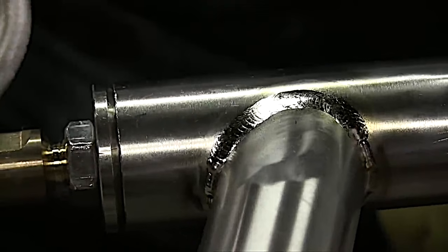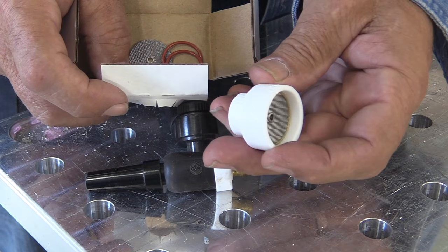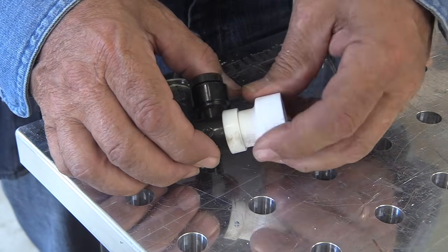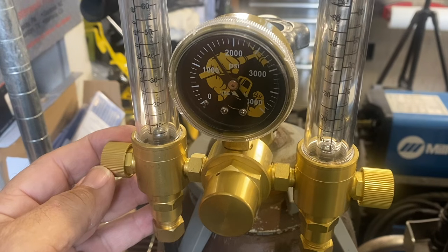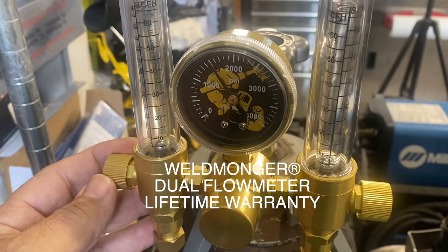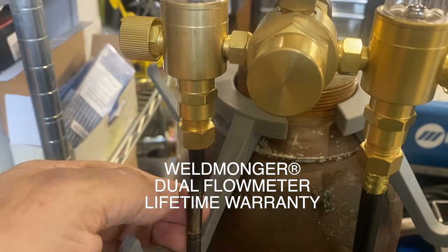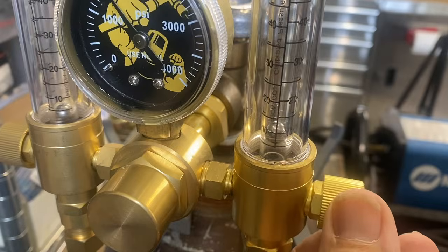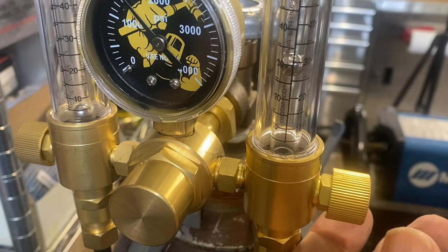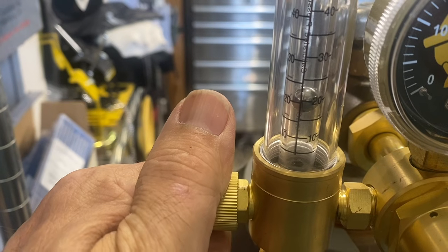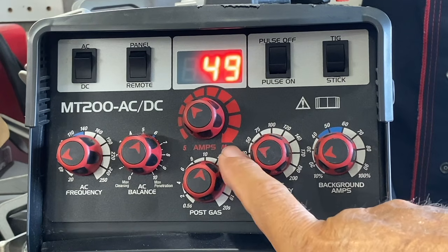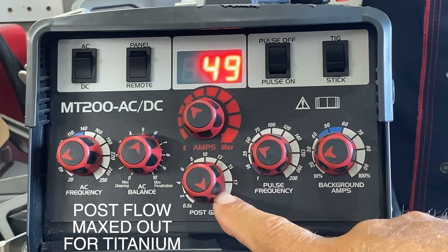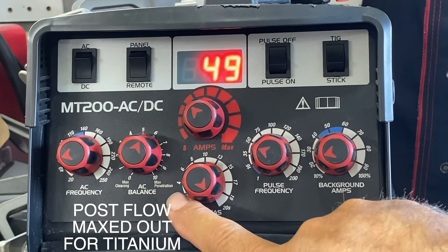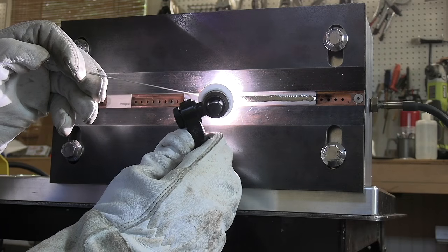No discoloration at all. There is an unbreakable high temp thermoplastic version of this cup that he calls a sippy. And if you got clumsy people around the shop, this might be an option for you. Again, you need a purge on the backside of titanium. We've got a new Weldmonger dual flow meter with lifetime warranty that'll help you get there. I'm going to crank this up to about 35 CFH on the cup and about 10 or 15 on the purge gas. We'll be using about 49 amps, and I'm maxing out the post flow here.